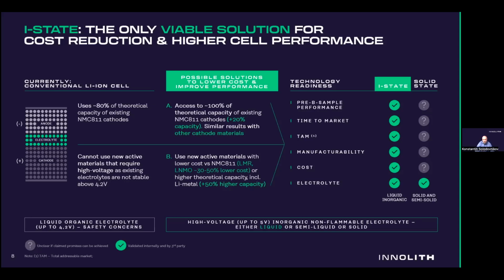And then, having the possibility to cycle our electrolyte to high voltages, we can develop additional systems where as cathode materials we can use manganese, which is abundant in nature, and this manganese can be used to replace nickel and cobalt, which are first of all expensive, and then also they are not widely available in nature. And with the use of manganese, higher voltage would be applied, cost of cathode material will be less, and the performance trade-off is significantly smaller than the cost advantage and performance advantage which we can achieve using our electrolyte.